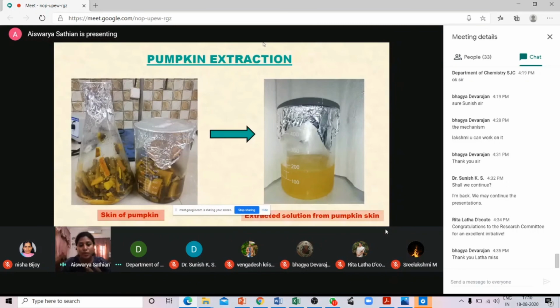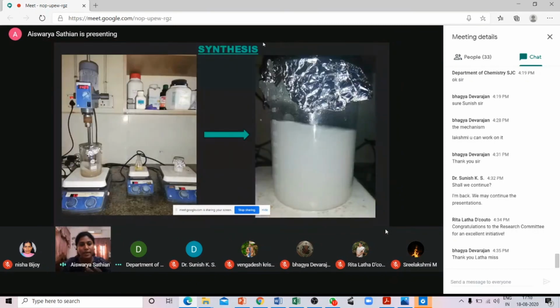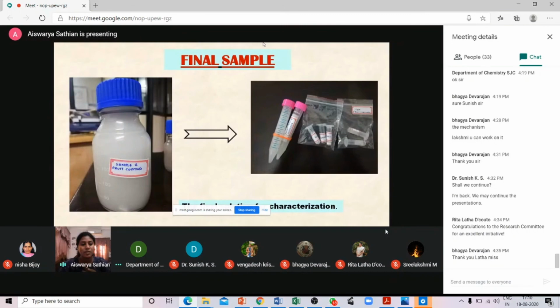This is the image showing the pumpkin extraction. This was the experimental setup. I used a mechanical stirrer for stirring the solutions to get a homogeneous mixture. I kept all the solution at a temperature of 55 degrees Celsius. This final sample, which I got from my synthesis, I gave it for characterization.